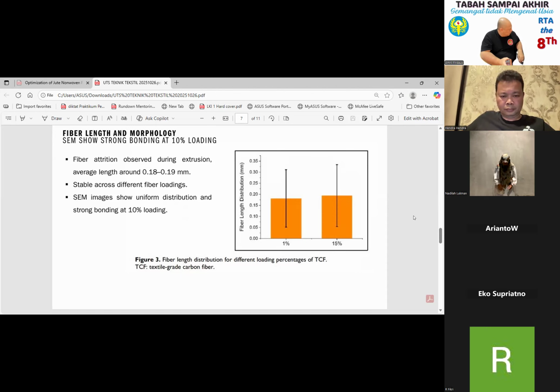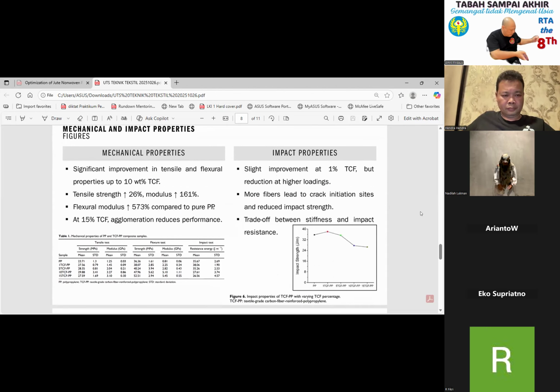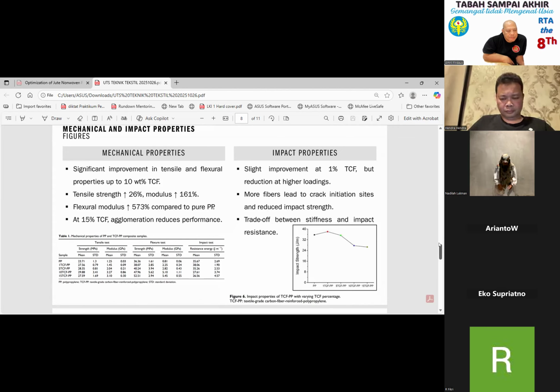Move on, Nadia, to the mechanical and impact properties. The tests include the tensile strength and modulus, the flexural strength and modulus, and impact resistance itself. The result is quite impressive here. When 10% textile grade carbon fiber was added to the polypropylene, the tensile strength increased by about 26%, and the tensile modulus, which represents stiffness, improved massively, 161%. That's more than double the stiffness of pure polypropylene.